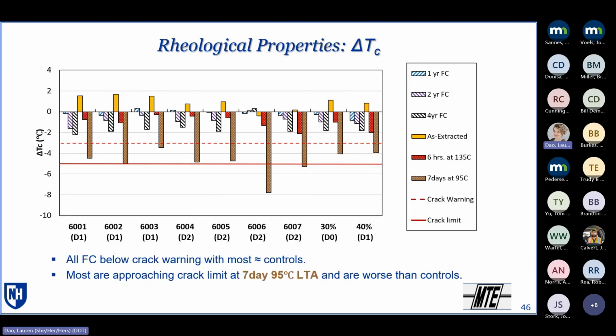In terms of the delta TC, again here, the graph is set up the same way. You'll notice that all of the field cores, up through 4 years, were below the crack warning limit. So we're not expecting to see any issues with the block cracking. And they're all very close to those control materials. It changes a little bit when we look at that longer term aging. Most of those materials are approaching or exceeding that crack limit at that longer term aging, and are starting to look a little bit worse than the control mixes.